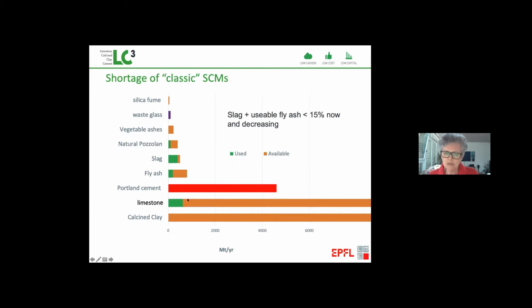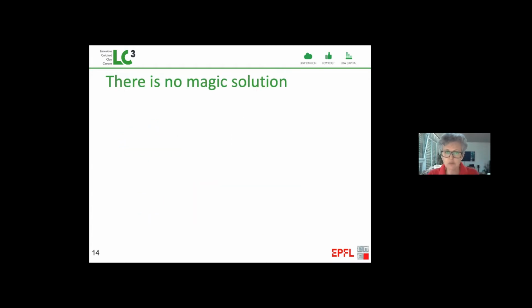Of course, we have unlimited amounts of limestone, but once we go beyond levels of addition of about 15%, then this is kind of just a diluent, and we then have to use more cement to compensate, which of course doesn't help much. I'm not going to go into the details on these materials up here, but the important point is that they are not materials available in very large amounts. So worldwide, the only thing we really have which can increase this level of substitution are clays, which can be calcined, and these produce very good substitute materials.